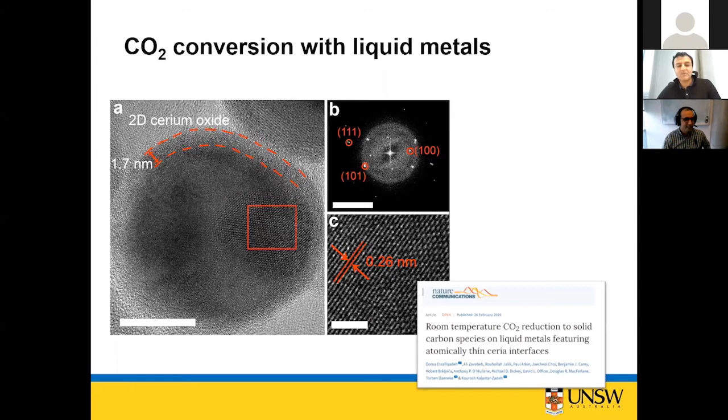It starts making nucleation and makes these nanoparticles inside gallium. Here we sonicated gallium to be able to observe very small droplets of gallium. We saw nanoparticles of cerium produced. Very interestingly, some of them go and attach themselves to the cerium oxide that is formed on the surface of these gallium droplets.